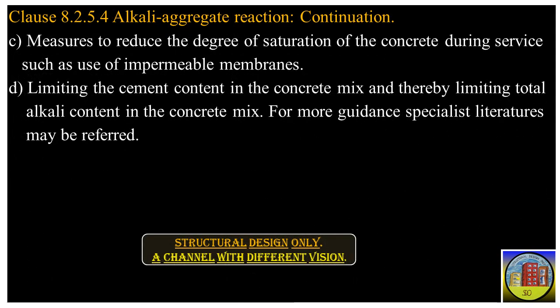Precautions for unfamiliar materials, continued. C. Measures to reduce the degree of saturation of the concrete during service, such as use of impermeable membranes. D. Limiting the cement content in the concrete mix and thereby limiting total alkali content in the concrete mix. For more guidance, specialist literature may be referred to.